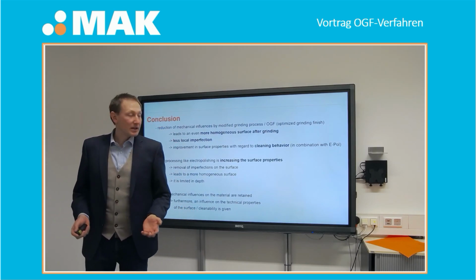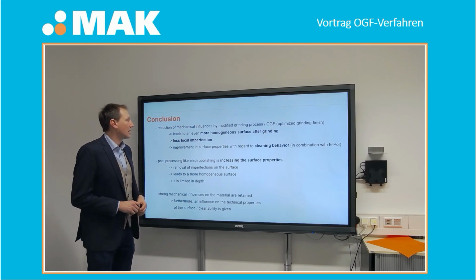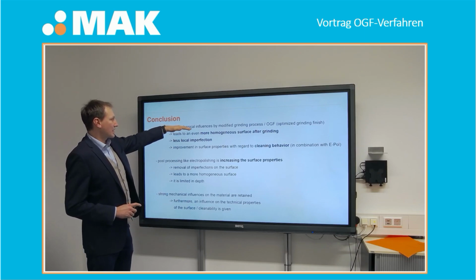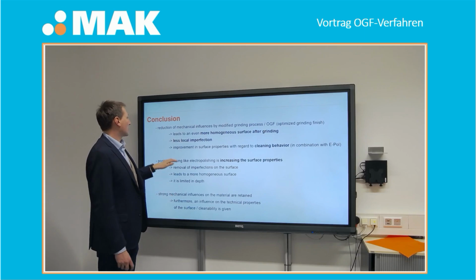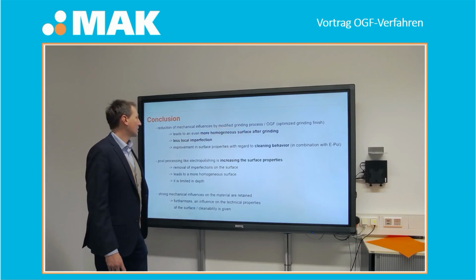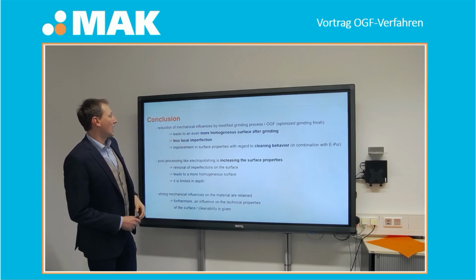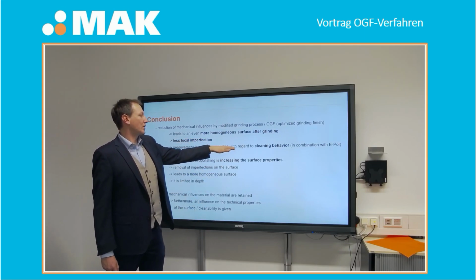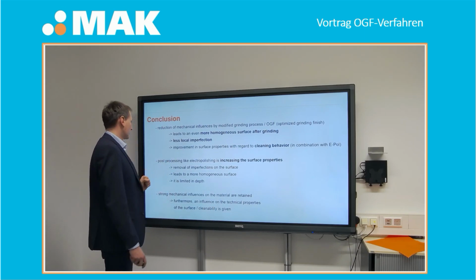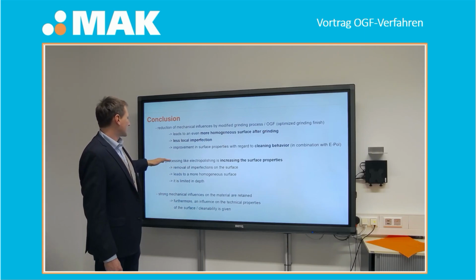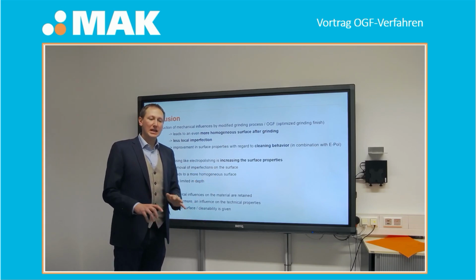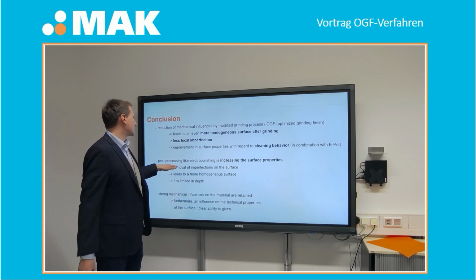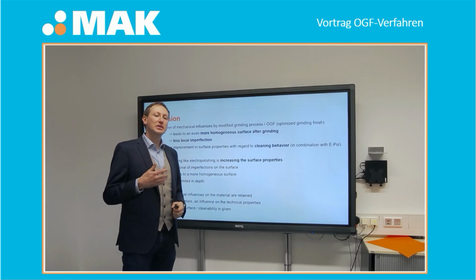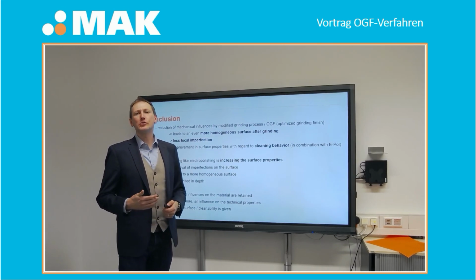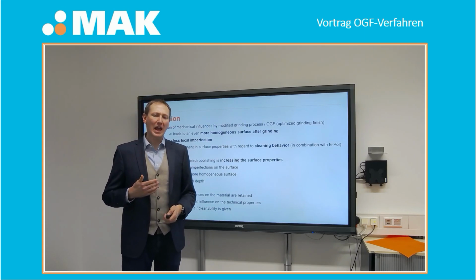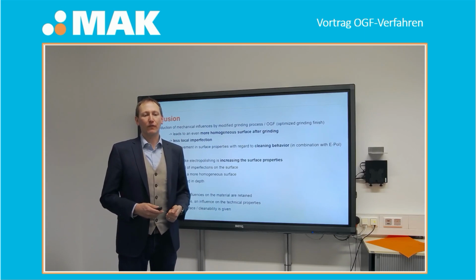So, to come to a conclusion, it's possible that we have a reduction of the mechanical influence in depth by the OGF process. This leads to a more homogeneous surface after the grinding. We have fewer imperfections left on the surface, and we have an improvement of the surface properties, especially regarding the cleanability behavior after electropolishing. This whole post-processing, like electropolishing, is always improving the surface properties. And of course, electropolishing is able to remove imperfections, but if you have imperfections on the surface from the machining process, you are unable to remove every kind of imperfection, and you are unable to remove every kind of dislocation inside the surface only by electropolishing.